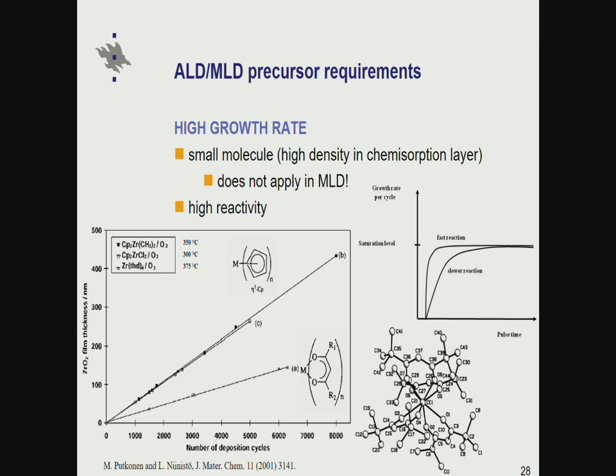Here is an example about zirconium oxide processes. These two curves here have been achieved with cyclopentadienyl compounds, and the third one here is obtained with beta-diketonate. These are not the smallest ligands, but still obviously they give a higher deposition rate. In this case, this is a molecule which is actually not the zirconium THD, but an analogous cerium THD, and it shows that we have the metal here, but around the metal there are lots of atoms as well. If you think about depositing either zirconium dioxide or cerium dioxide, out of all the atoms in the molecule, only 3 are to be incorporated into the film: the metal and 2 oxygen atoms. All the rest are there just to make the compound volatile. Obviously then it's better to have smaller ligands and pack them more.